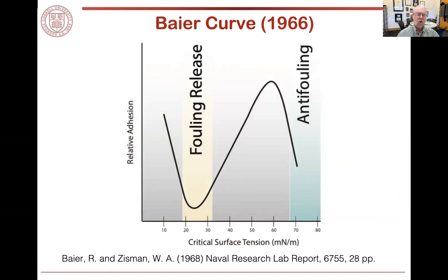Now, this is a situation that's been known for a long, long time. Back in the 60s at the Naval Research Lab, Baier and Zisman worked together. They studied bacteria growing on surfaces. And what they were able to show was that in the range of about 20 millinewtons per meter, fouling release took place. These are non-polar surfaces, generally silicones and fluorinated materials. And at higher surface energies, higher surface tensions, anti-fouling behavior took place, and these were often more hydrogel-like surfaces. They made no study of the mechanical properties of the materials.